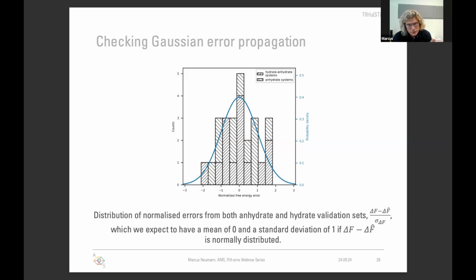That is a blue curve. And if you compare the histogram that we get on our data to the blue curves, then you will realize that within our statistics, so we only have 25 cases we really trust, this actually pretty well follows Gaussian error propagation. So at least our assumption of Gaussian error propagation is reasonable. And our compounds actually also cover a decent size range.